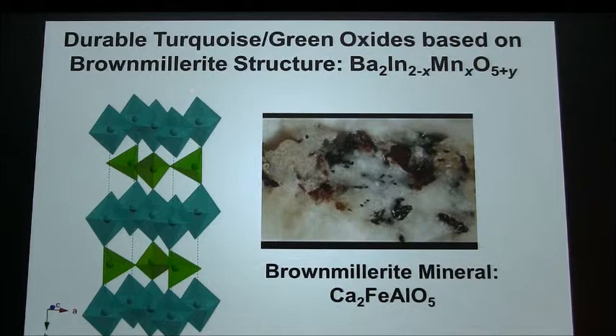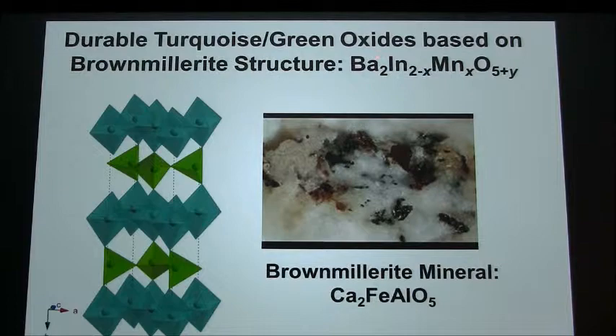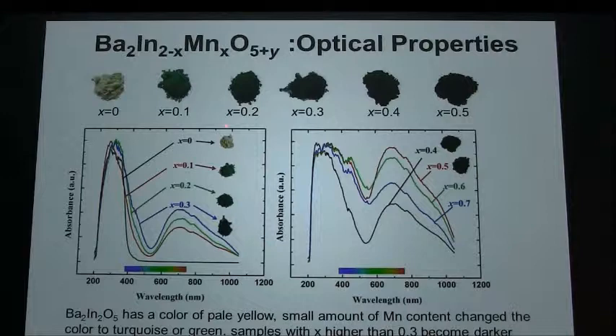Calcium phosphate pigments are not very stable to acid, because when you put acid, they dissolve. But in this case, these compounds are highly stable. So we chose that material structure, and we put manganese in the indium site, with barium instead of calcium. What we found was turquoise pigments, which you can see are mostly greenish blue. We can change the color of the pigments by changing the manganese to indium ratio.